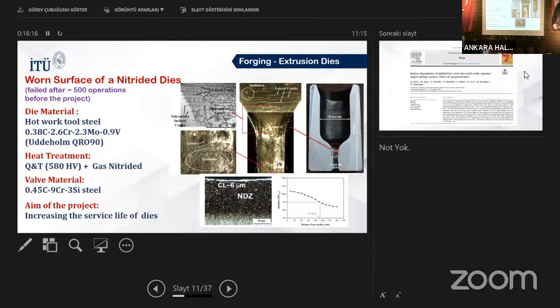Now we have detected such a white-colored region. This is a nitride, right? And within it, we have got the nitrogen, and the thickness was about 6 microns. The hardness variation within the nitrogen diffusion zone follows this one. So this was our starting point.